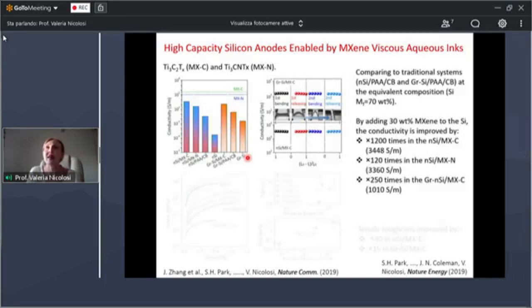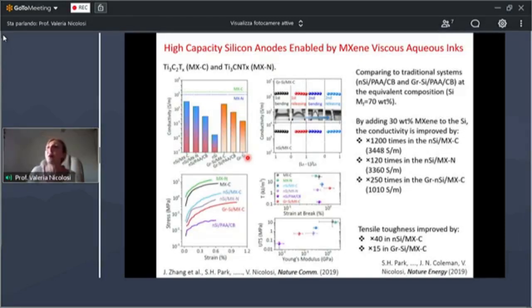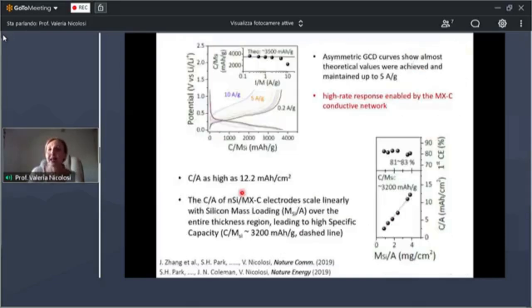Do these devices work? They work very, very well. We published this in Nature Energy a couple of years ago. Only by adding 30% of MXenes, you do have an improvement in conductivity of about 1,200 times. And if you look at the tensile toughness, well, you can actually get, again, with about 30% of MXenes, about 40 times tensile toughness, which is quite a record. And that is what ensures the mechanical stability of the electrode.